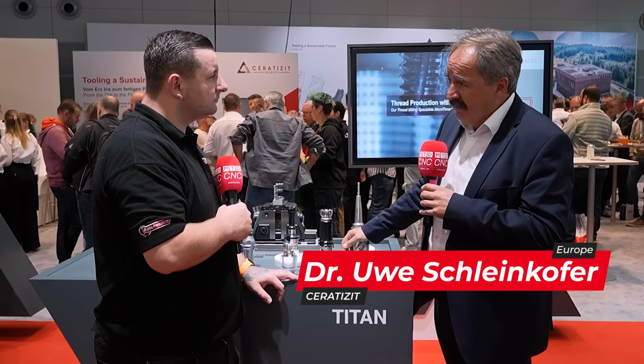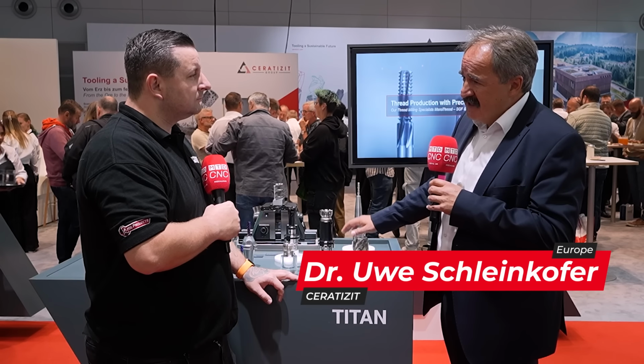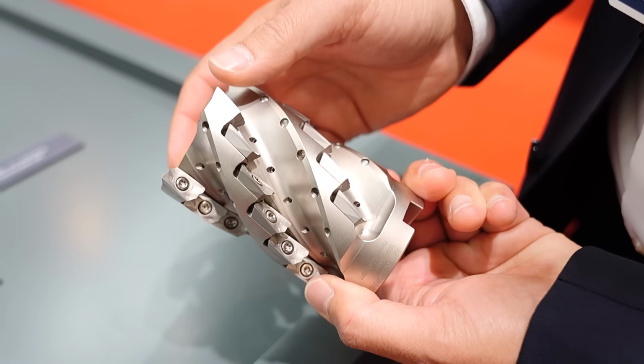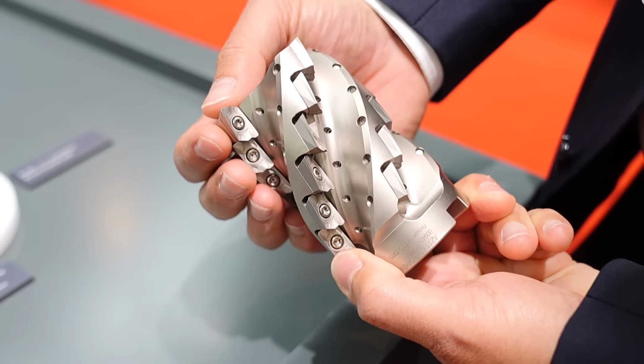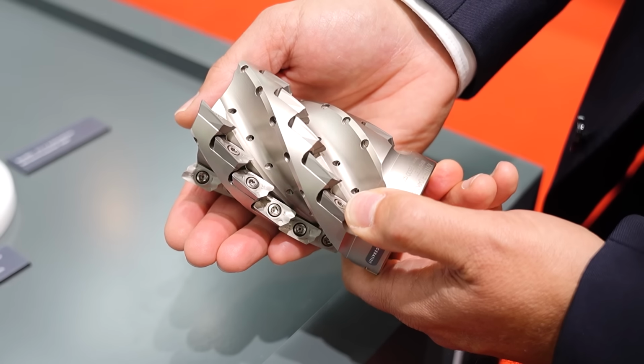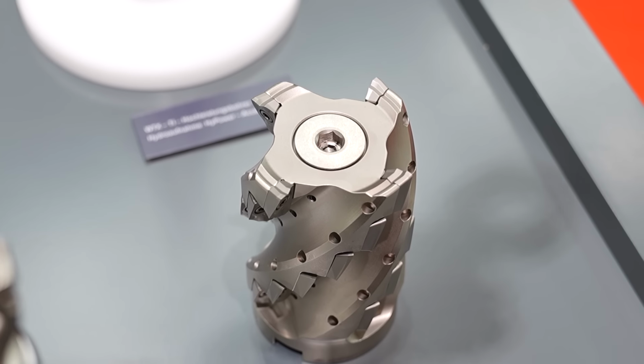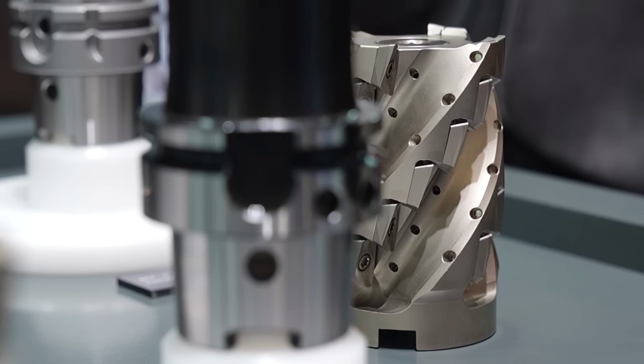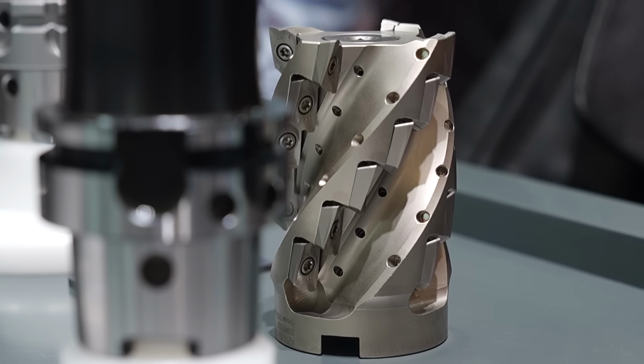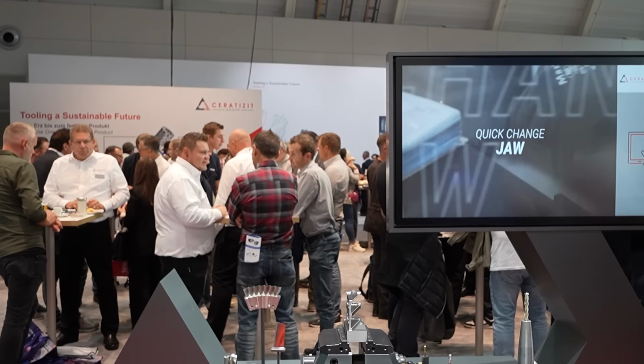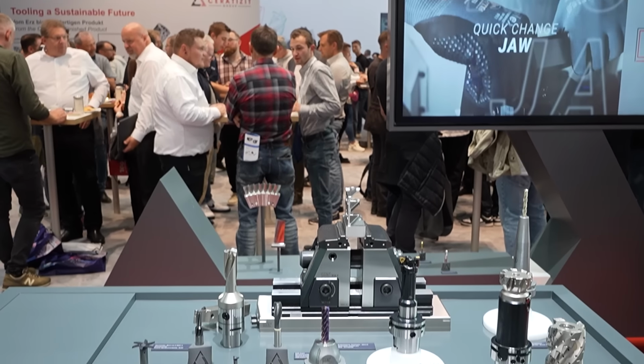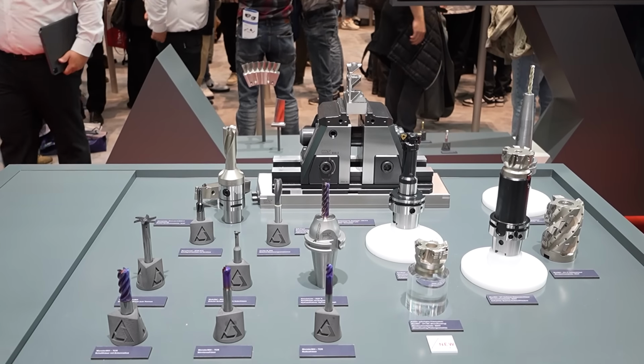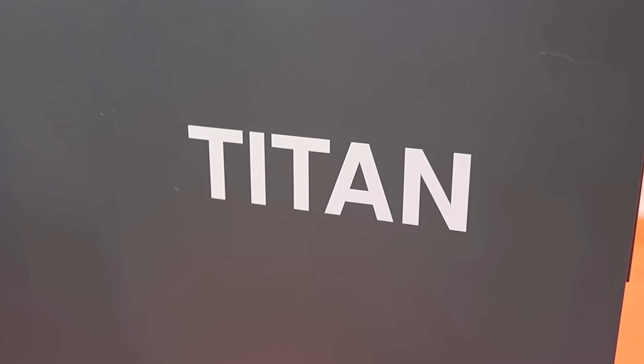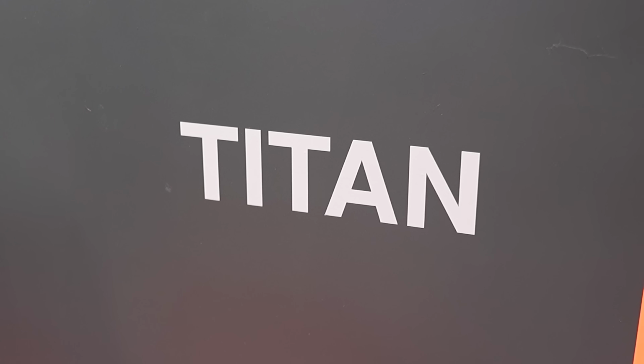And for pocketing, this tool is the right choice because it has a very, very high chip volume, which you can create on titanium. So what are some of the problems people face when machining titanium? Titanium is a mess, let's put it that way. It has very high work hardening. That means the more material you want to remove in a specific time frame, the more resistance of the material you see. And therefore you need high strength, high chemical stability, and you need to resist high temperatures. This combination is quite tricky to achieve in titanium.